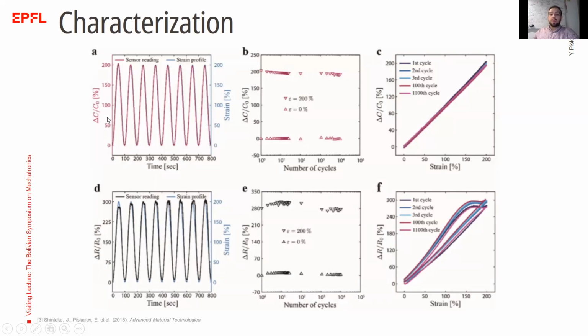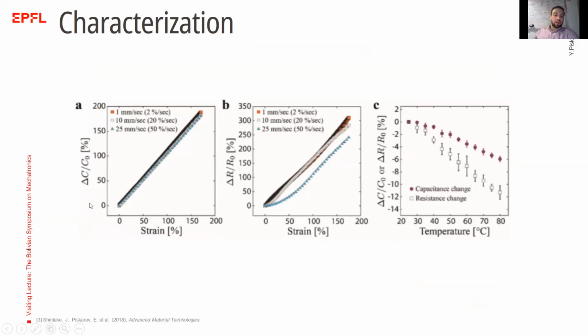We collected data on the repeatability. We took a look at how the capacitance is changing, how the resistance is changing under different strains. And as you see here, what is interesting is that we have some kind of hysteresis in the resistance measurement and almost no hysteresis in the capacitance change. So that was already an advantage of capacitance measurement, right? Then if you take a look, for example, at the strains at different times, you will see the response of the capacitance measurement approach is faster than the resistance approach. And also, if you look at the change under different temperatures, it's much less in the capacitance change than in the resistance change.